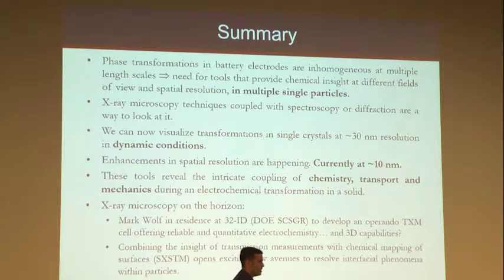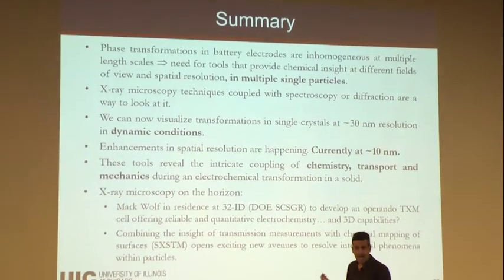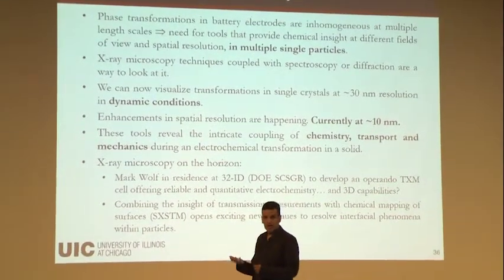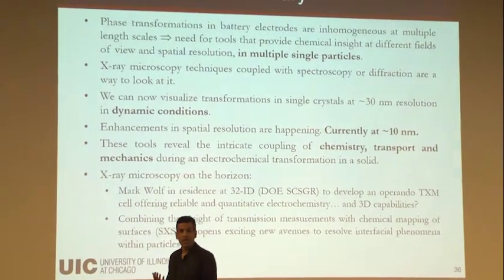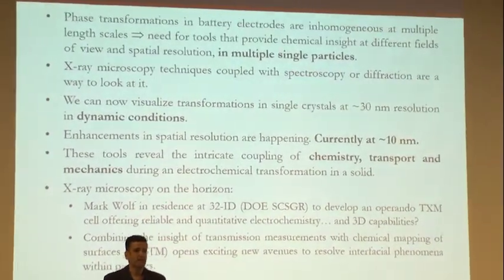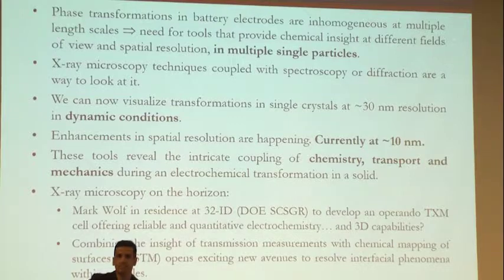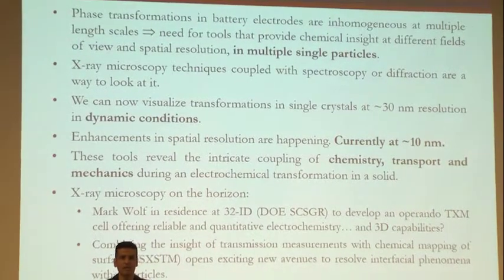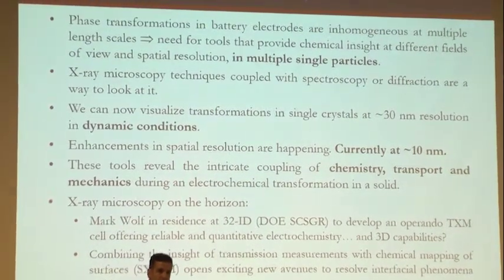We do this with X-ray microscopy. It's beautiful what you can do with X-ray microscopy today. You can combine with spectroscopy, combine with diffraction. You can do, or we hope we're going to be able to do, more surface-sensitive measurements. And because you can do this in the hard X-ray regime very often, you can design an operando cell that allows you to follow the reaction as it happens with a chemical image. We can go down to 10 nanometers.